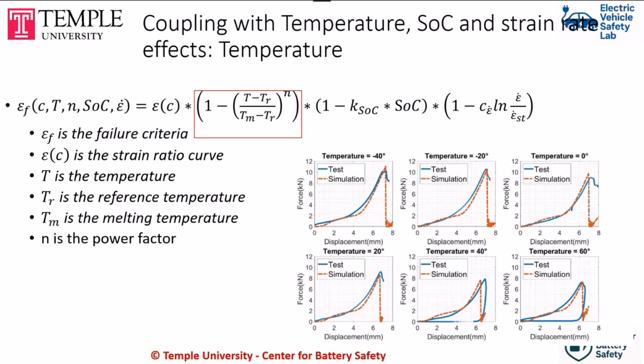You can see for batteries between -40 degrees and 60 degrees, the peak force is changing from 12 kilonewton to under 8 kilonewton. So really, you cannot just have one failure criterion at room temperature and use it for all these different temperatures. And these are not temperatures out of the normal range. These are the normal operating temperatures for batteries, because they do heat up during use, and they can also be in cold temperatures, and these are the temperatures that are acceptable for batteries. So you really need to include that temperature dependency.